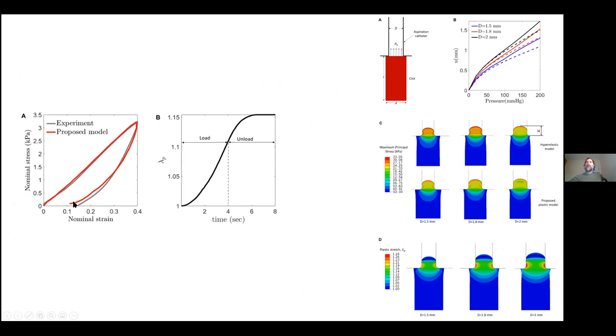And one example of where this can be important is in simulating aspiration. So here are some initial simulations of clot aspiration. This is an aspirator. We apply a pressure to an idealized rectangle or a cylindrical blood clot. And we can see that we're getting permanent deformation, particularly at these very high deformation regions towards the corner of the aspirator. So this changes our prediction of how much the clot goes into the tube.